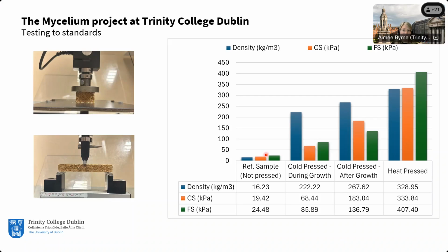So you can see in orange there are compression tests, and in green there are flexural tests, which gives an indication of tensile behavior. In our reference sample, when we cold pressed after halfway of growth, and then when we cold pressed after full growth or full colonization, you can see there are big jumps between each of those phases. And then in the heat pressed samples after full colonization, there was a much bigger jump there at the end.